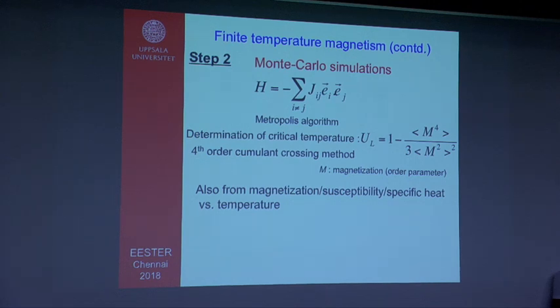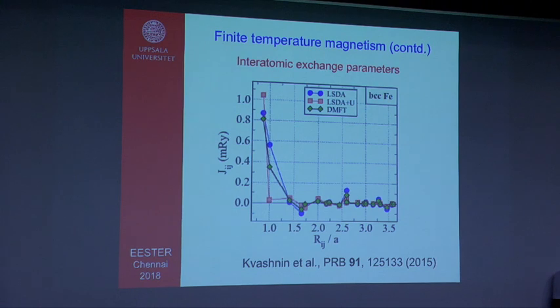So first let me show you something for a very simple elemental ferromagnet, which is BCC iron. These are the interatomic exchange parameters calculated as a function of distance between a pair of moments. Three things have been shown here. One is from the local spin density approximation, one is adding a U to that, and one is with dynamical mean field theory. You can see that more or less they follow a similar trend, but there are certain differences because of the different approximations that we use. Sometimes with static mean field or dynamical mean field the results are different, and there are lots of important discussions behind this, but let's not go into detail.